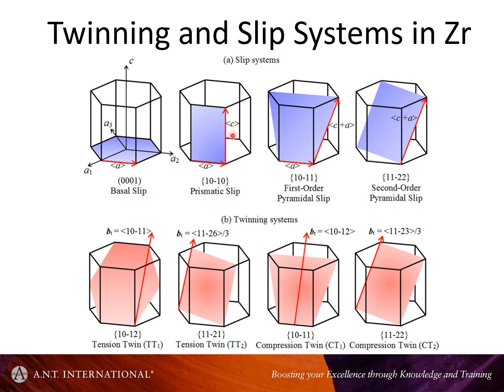On this thing that I stole off the internet, it talks about a C dislocation, but that wouldn't be a slip dislocation. It's not possible to get C slip. But it is possible to get A slip both on the basal plane and the prism plane, prism 1 plane. It's also possible to get A slip on this first order pyramidal plane. So when I give this presentation live, I'll have some ball models and I'll be able to demonstrate simply how slip operates on all these different planes.